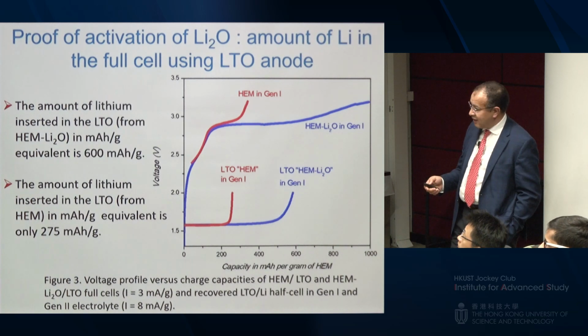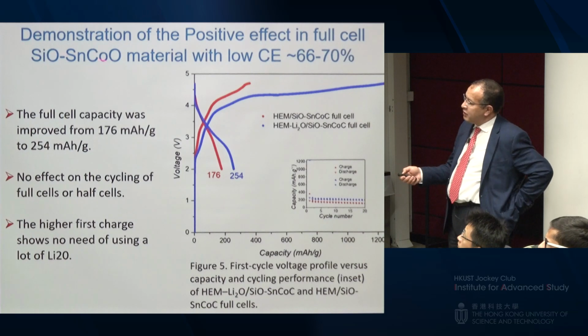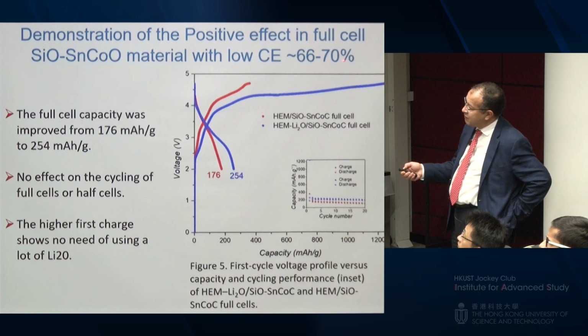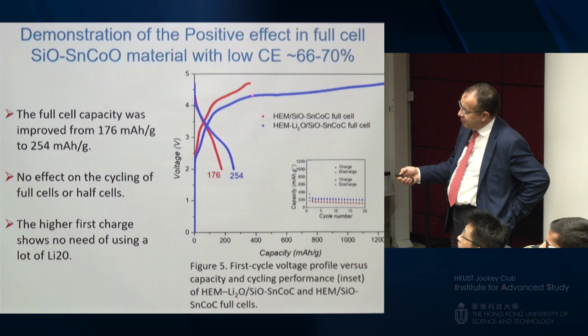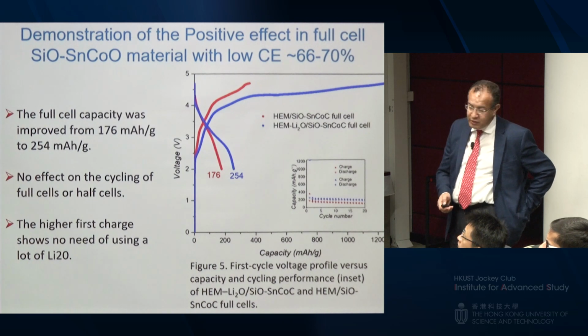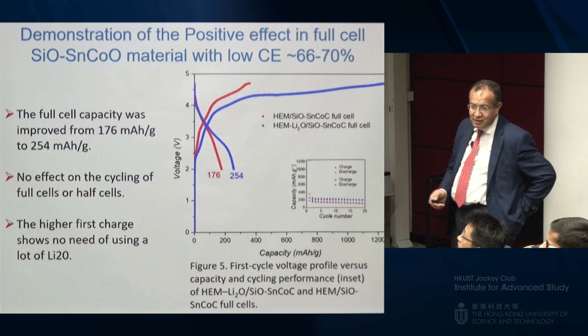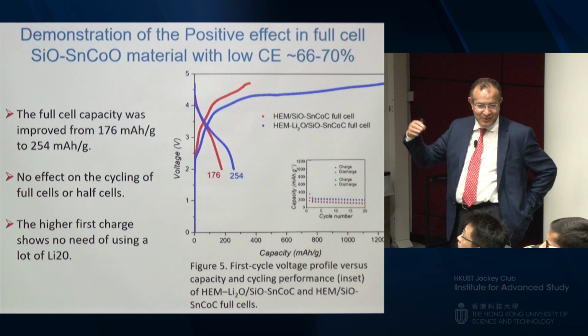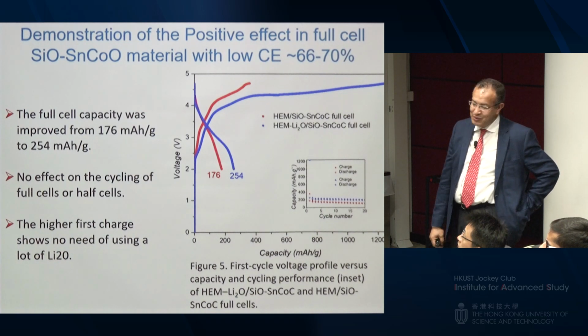And we took an example of a poor efficiency material that has 70%. We use it without lithium. You can see we use a cathode that should give us 250 milliampere per gram. That's the high energy lithium-rich, manganese-rich cathode. But we got only 176 because we lost a lot of it to the silicon to take care of the